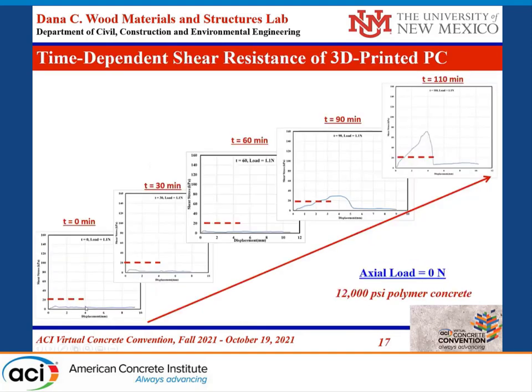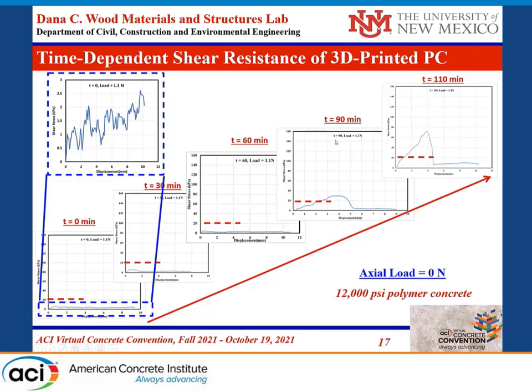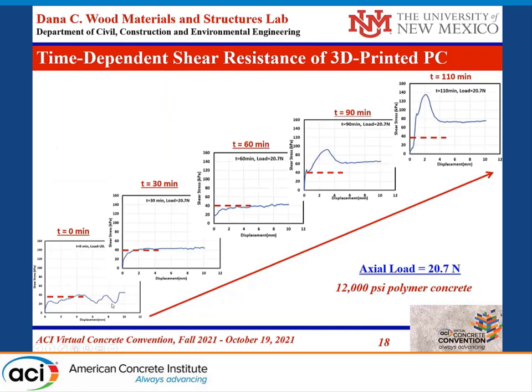We can see here the evolution of shear strength of the polymer concrete with time — starting at time zero of just mixed material, to about 110 minutes. There is almost zero change early in time — very small evolution within measurement resolution — but between 60 and 90 minutes of the selected mix, a significant change in shear stress happens. We repeat this with different applied normal stress values and still see the evolution is nearly constant from time zero to 60 minutes, then a significant change begins between 60 and 90 minutes.